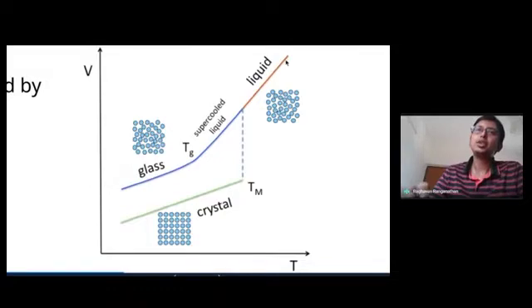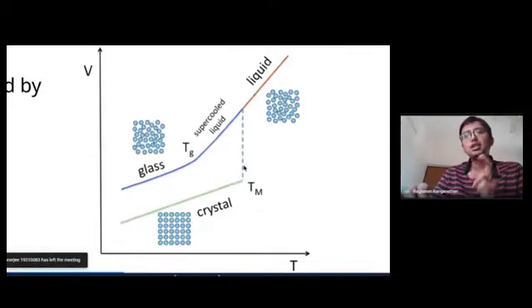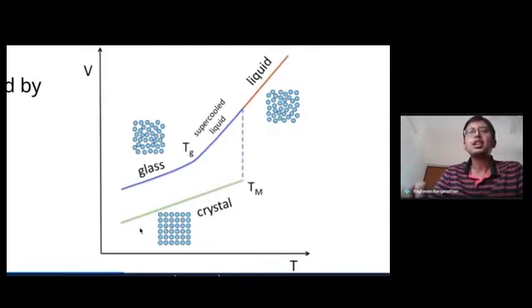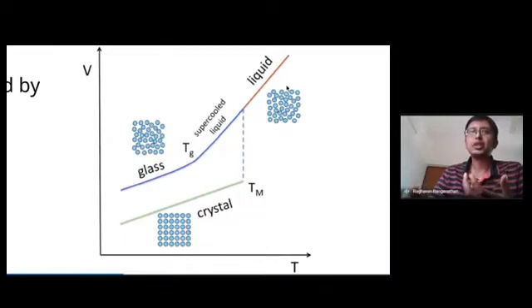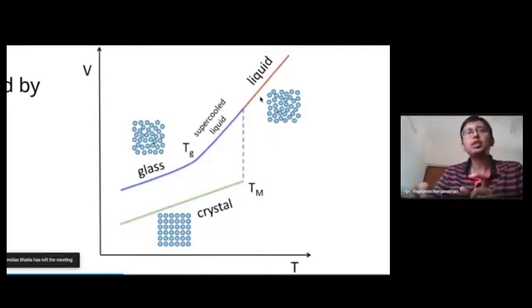And then if you cool it slowly, what thermodynamics tells you is there is a transition point denoted as Tm, which happens to be the melting point, where there is a sudden decrease in the volume, or alternatively, an increase in the density. So from an equilibrium perspective, the liquid gets transformed to a crystal. This crystal has a lower volume, a lower energy, and is more stable than the liquid. But what's very interesting is, if you take the same liquid, but instead of cooling it very slowly in an equilibrium process, you cool it very rapidly and supercool it, meaning you cool it below the melting point, it so happens that you can preserve the glass structure, or in other words, the liquid structure.